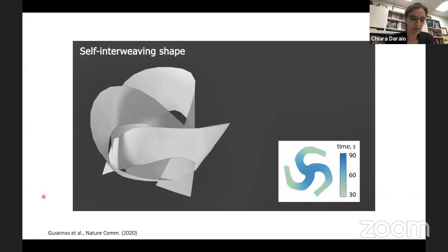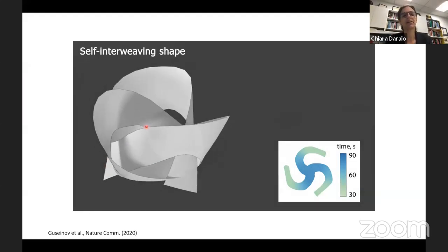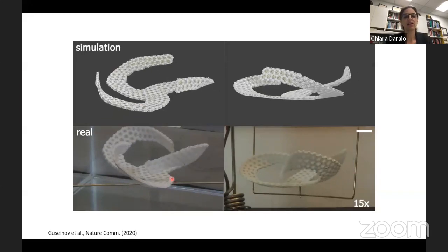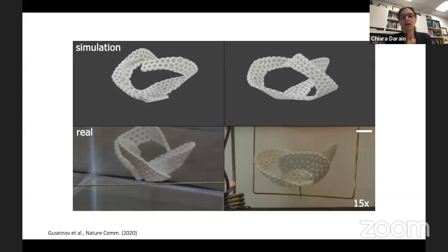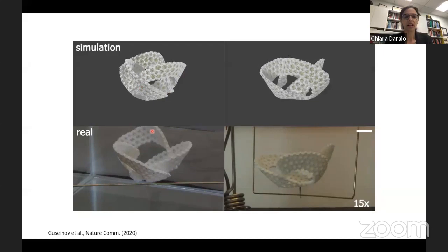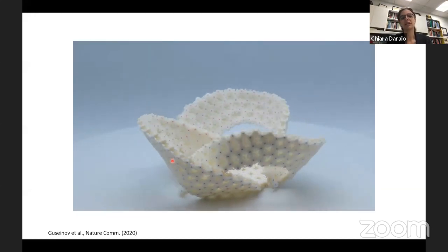But the lotus leaf was something that was shown before. So we asked ourselves, well, can we make more complex shapes? For example, can we have ribbons that self-knot? In this case, we called it a self-interweaving shape, which is a lot more complex because the time of actuation really needs to be spot on in order to avoid collisions in the knotting. And you can see that once again, here are the simulations, and below you see the experiments. You can see that the three ribbons are actuated in different places at different times, and we were indeed able to show